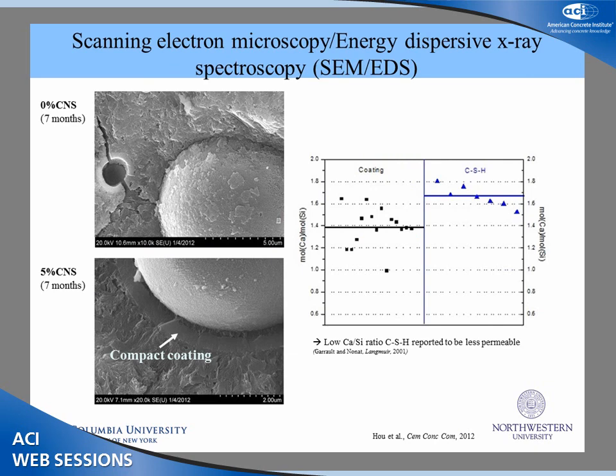We also found in SEM results that with 0%, this is the plain 40% fly ash paste, and then this is with colloidal nanosilica at 5%. These are both at 7 months. And the big difference here is this compact coating that develops around the fly ash particle. And EDS results indicated that this compact coating, which consists of CSH, has a lower calcium to silicate ratio. And it's been reported that low calcium silicate CSH is less permeable. So with the addition of nanosilica, it's developing this impermeable coating around the fly ash, and that hinders later age strength gain. And so this helps to explain why the nanosilica is leading to a reduction in rate of strength gain over time in our fly ash systems.